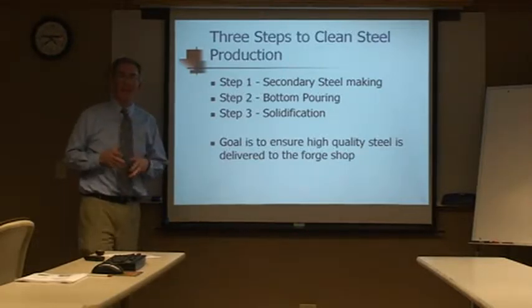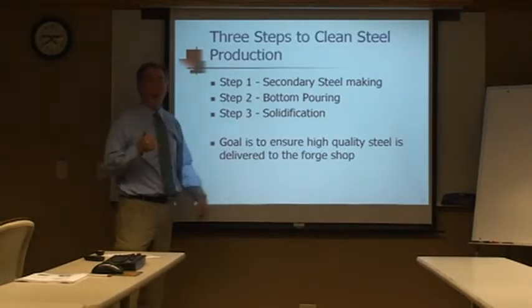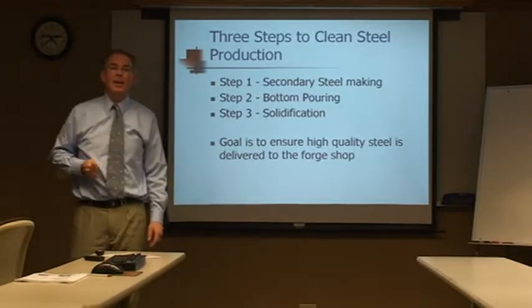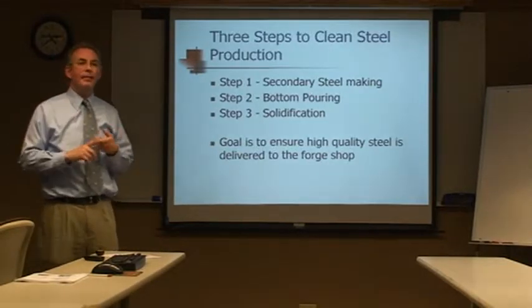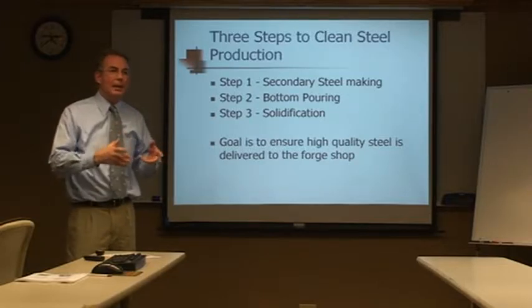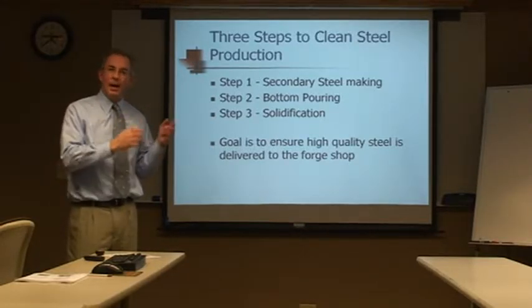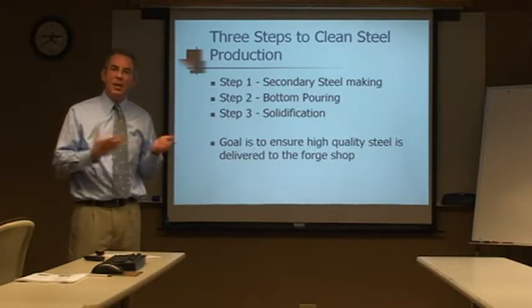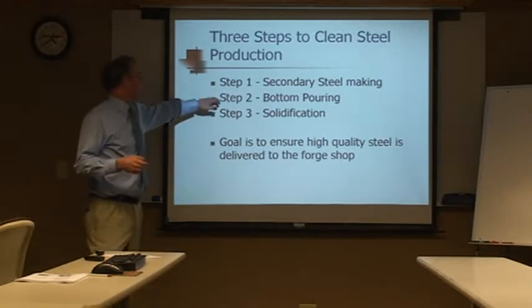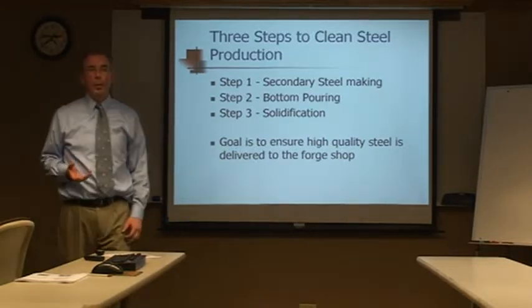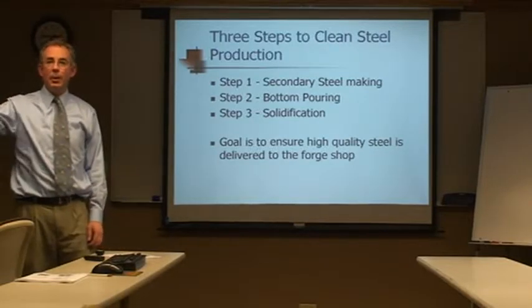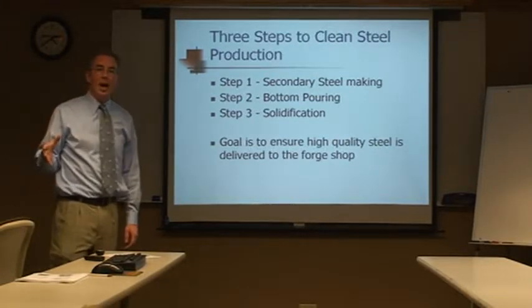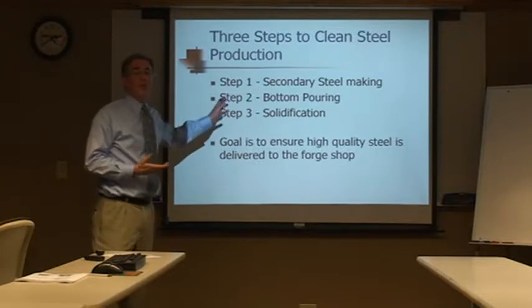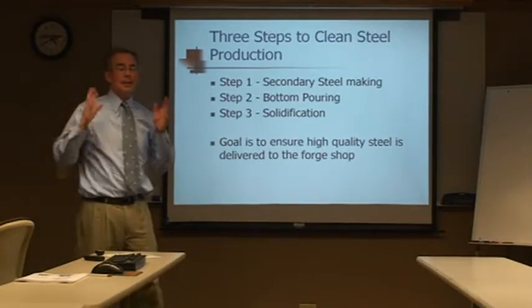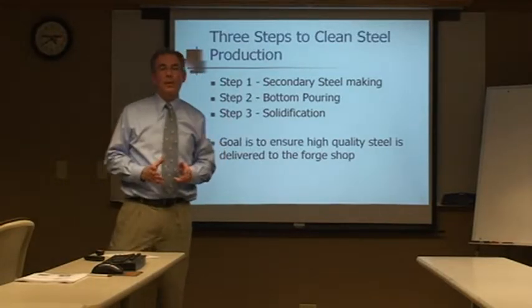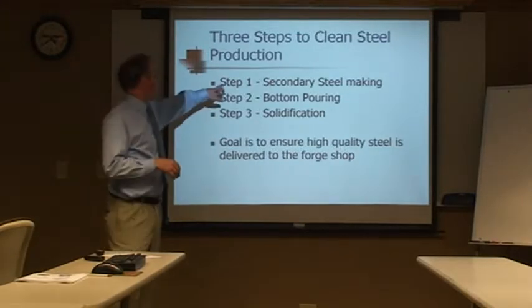We were talking, break it down into 3 sections. Step one, clean steel practice and secondary steel making. That's starting effectively tapping out of the arc furnace into the ladle refining, and deoxidation of the steel through melting. Step 2, clean steel practice during bottom pouring, making sure when we pour the steel, like Dan had said, we're worried about exogenous inclusions. We have $100 million worth of steel making that can make the cleanest and best steel in the world. That would be step 1.